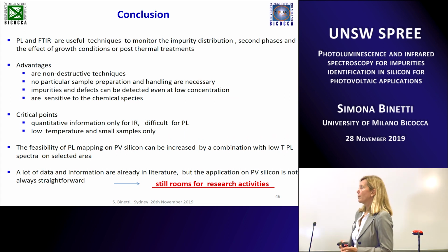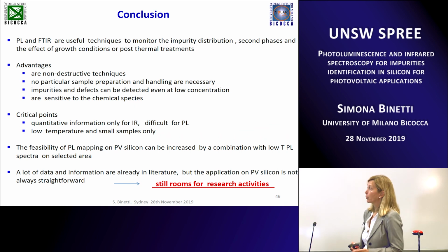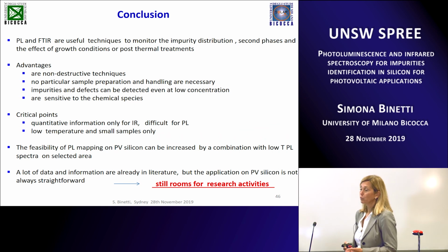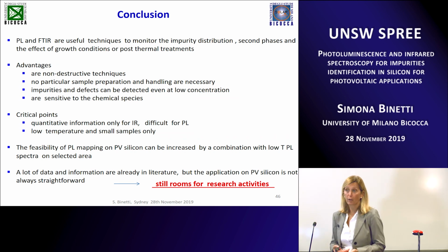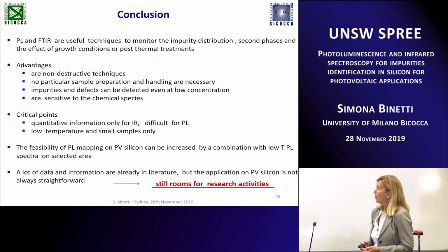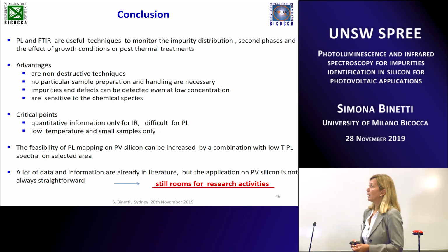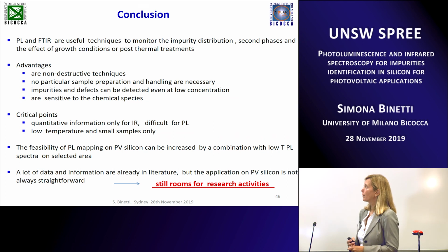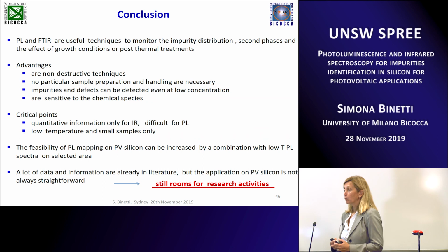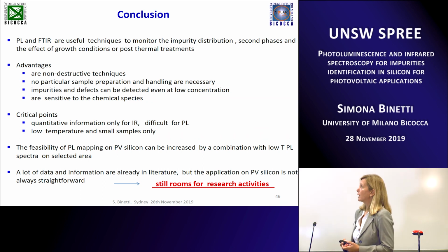Of course, there are some critical points with this technique because it's difficult to have quantitative information. Usually you have to perform photoluminescence at a low temperature and also on small samples. So I think that the feasibility of PL mapping on PV silicon can be increased by a combination of PL mapping also with micro PL at a low temperature. And so we have a lot of data and information in the literature. We have to check it carefully.